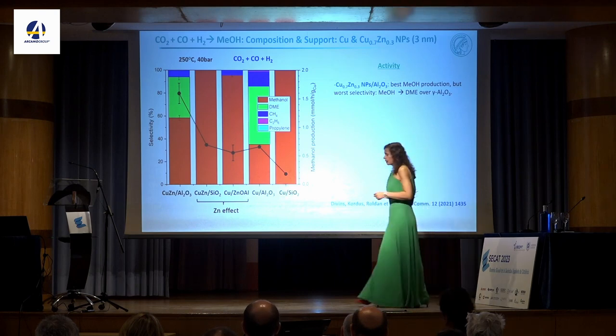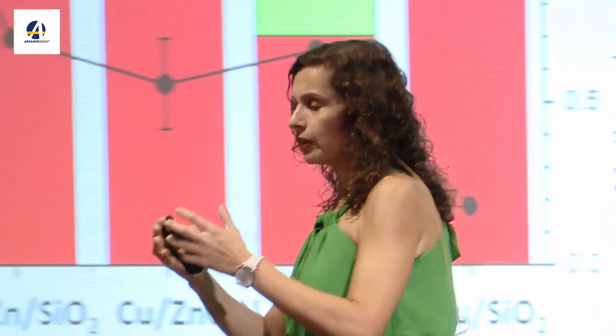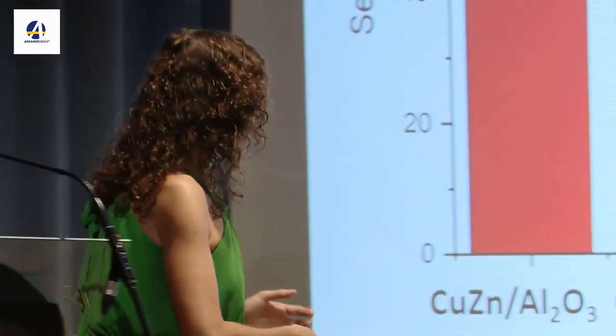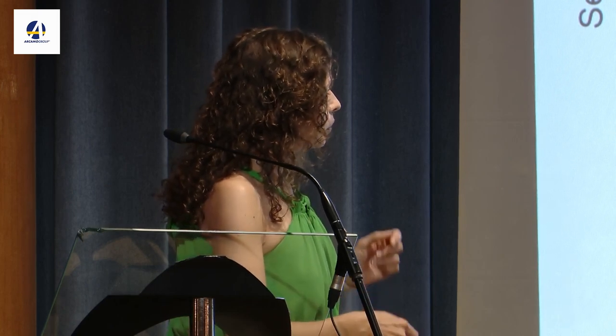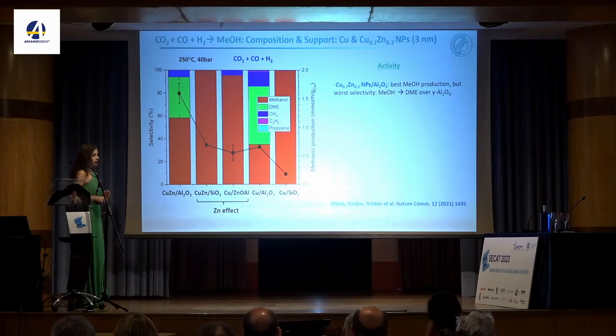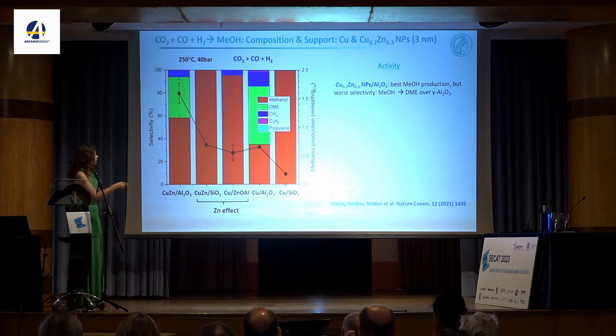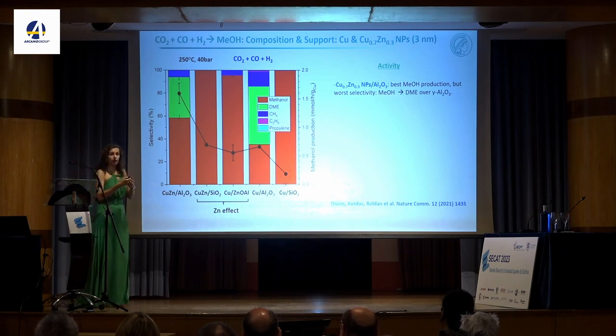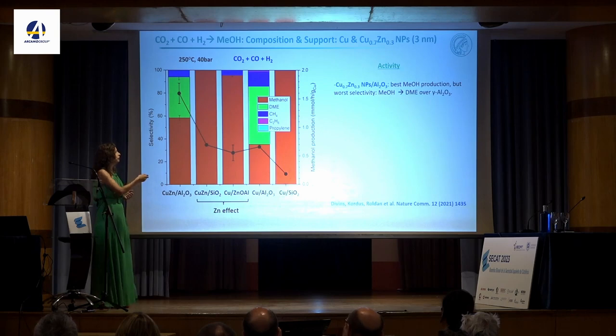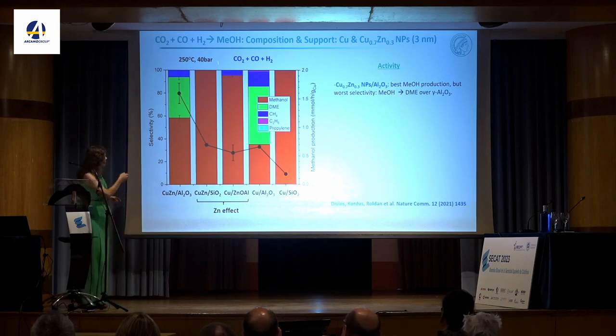Now we have these very well-controlled nanoparticles, and we wanted to see what is the role of the support. And we compare the cases, for example, where you have zinc only in close contact with copper as part of the nanoparticle. These are about 3 nanometer particles. And then we did the same with pure copper on the traditional zinc oxide alumina. In black is the methanol production activity, and you can see that these two samples have very similar production of methanol, even though the one that had copper zinc nanoparticles only had about 30% zinc in these micellar nanoparticles. So we didn't need to have the zinc as part of the oxide support. The selectivity is also very good.